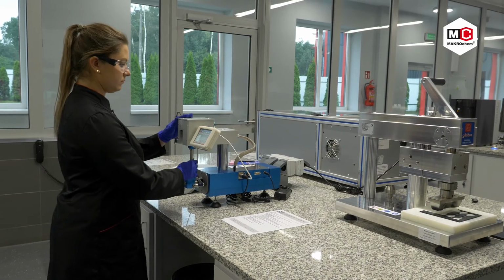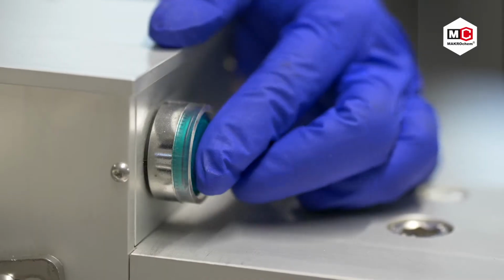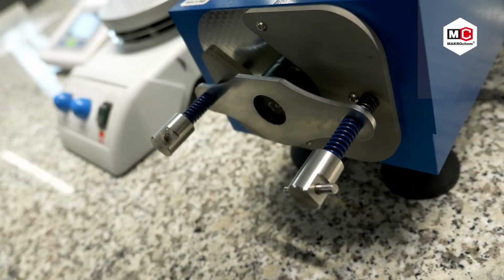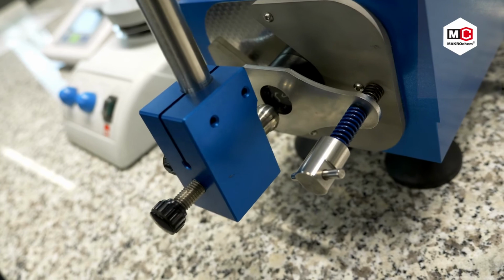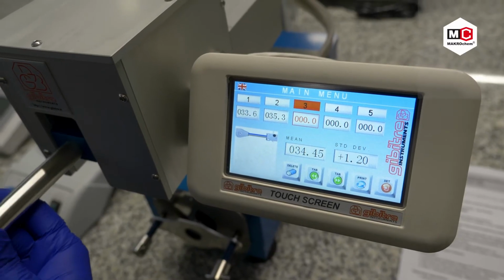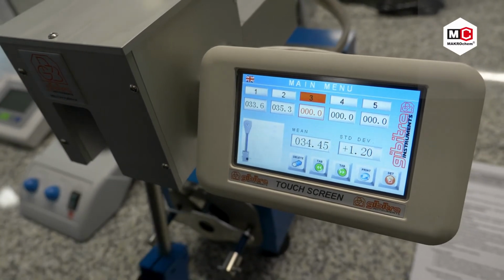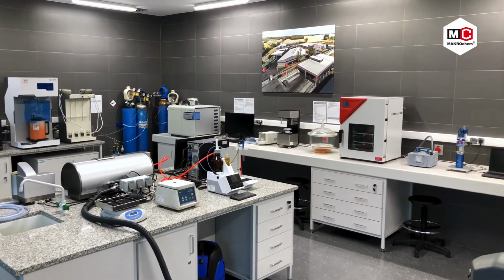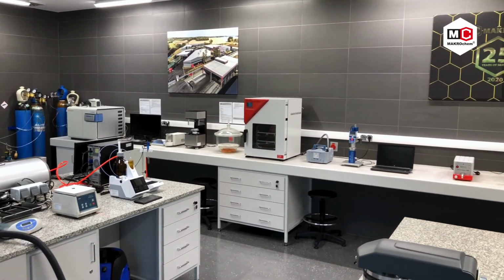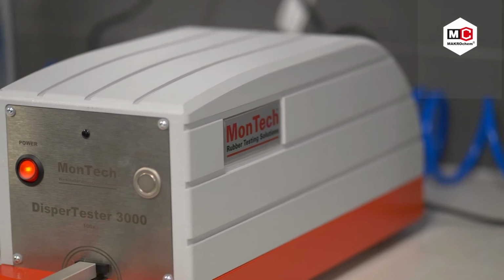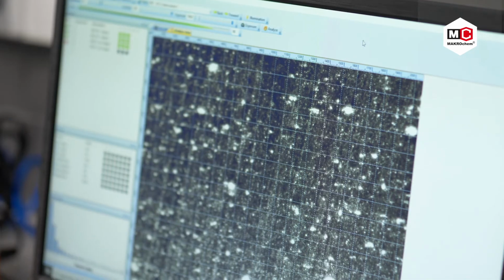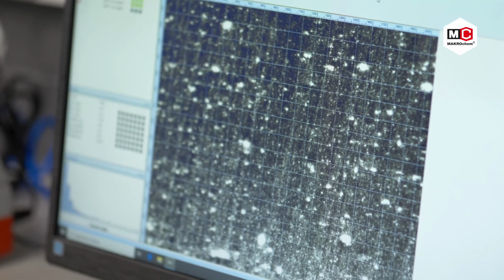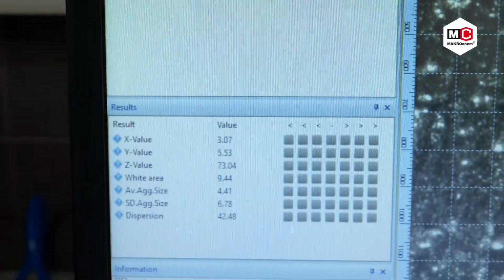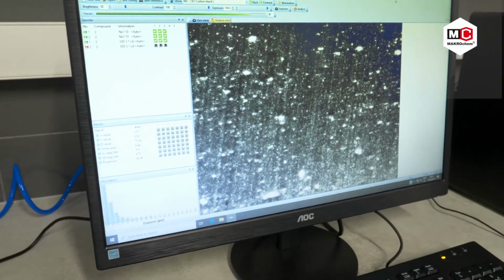Another feature of rubber compound that we measure is flexibility of the vulcanizite using Schob method. It is one of the methods evaluating viscoelastic properties important in dynamic applications of rubber. Using optical and scanning microscopy, we test the morphology of rubber, to evaluate macro dispersion of the filler. At a specified magnification, an image of the cross-section surface is recorded and dispersion ratio calculated in percentage points.